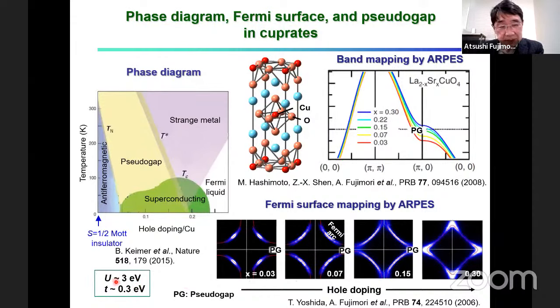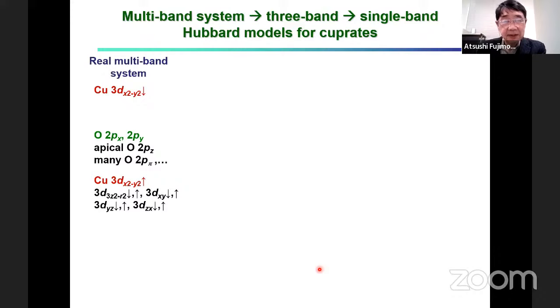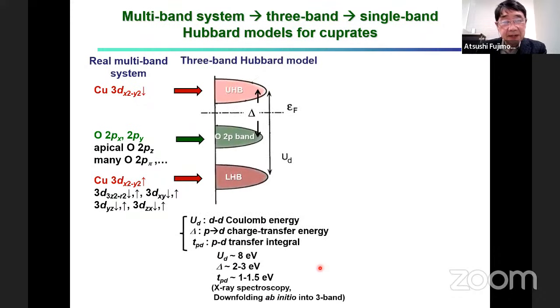Okay, I should also mention that the magnetic properties can also be understood with this parameter through the superexchange coupling constant J, four times t squared over U, describing the Mott insulating states. So almost every physical property can be understood within the single-band Hubbard model.